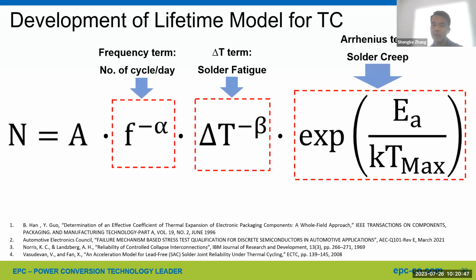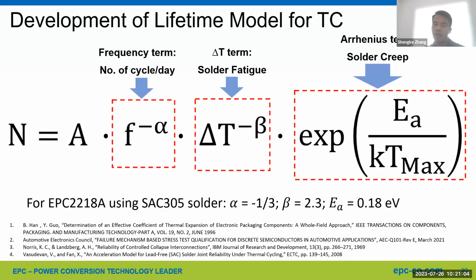Lastly is the Arrhenius term, which is primarily to model solder creep wear out mechanism, because solder typically fails faster when the hot extreme temperature is higher, which is when Tmax is higher. So here are the parameters for the lifetime model of EPC2218A using SAC305 solder material.